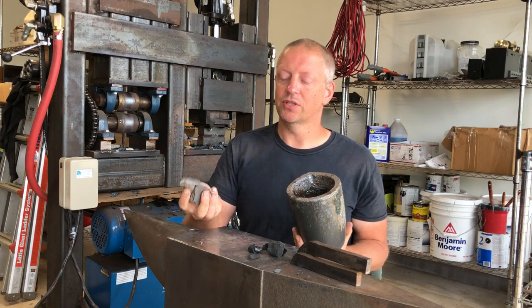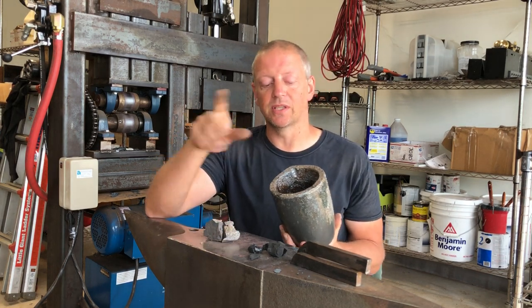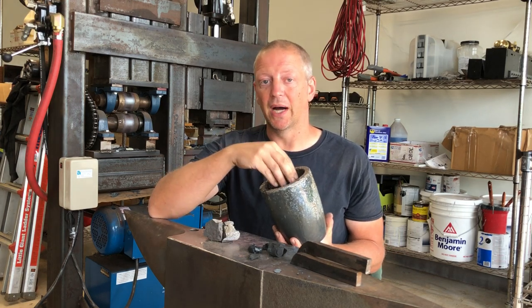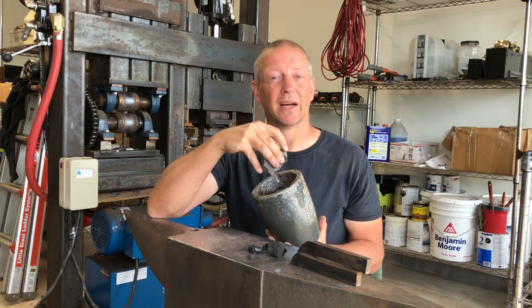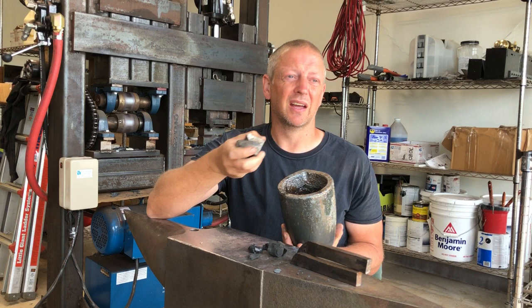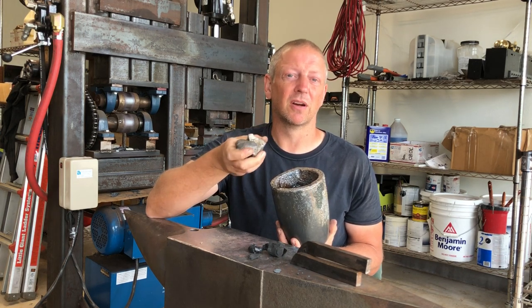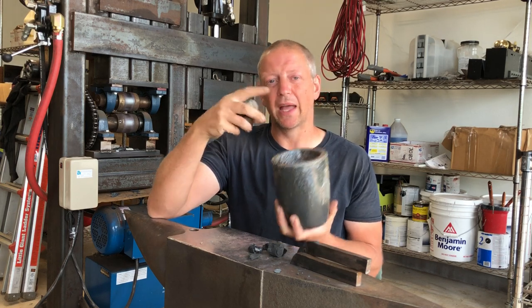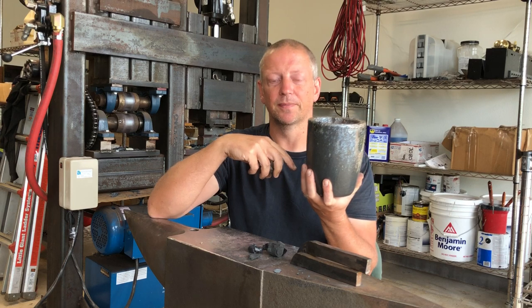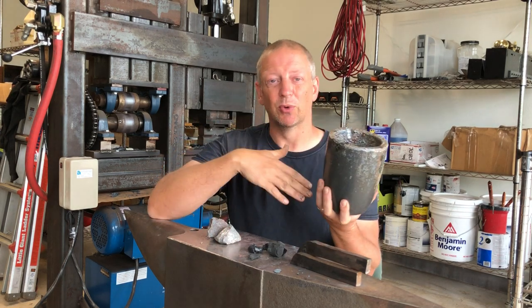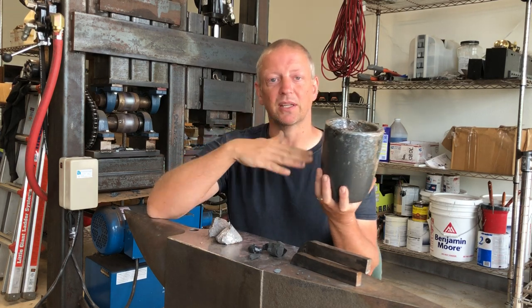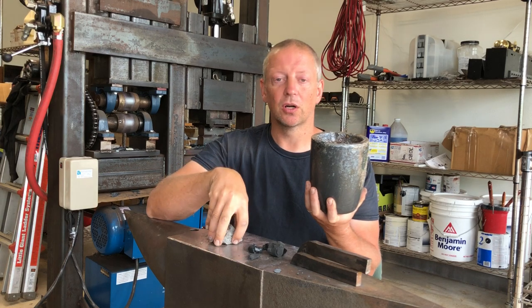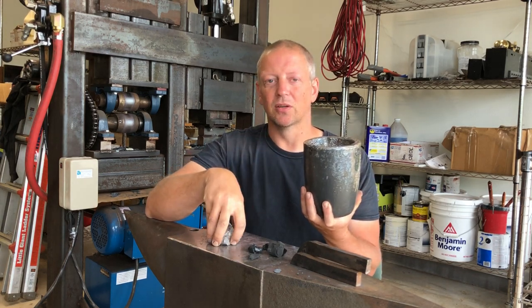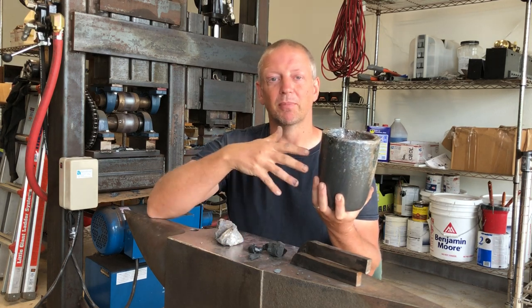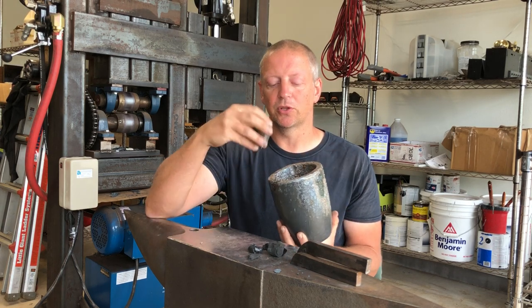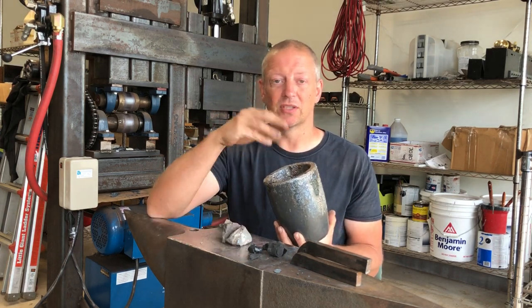By contrast, using the pig iron, what I want to do is actually put my mild steel or wrought iron in the bottom of the crucible with my pig iron on top of it. The pig iron will melt at, let's say, 2200 degrees Fahrenheit, and then trickle down through your mild steel. What that does essentially is bring carbon pretty evenly to all of your surfaces early in the process. That carbon then works its way inward, and you get a much faster melt.